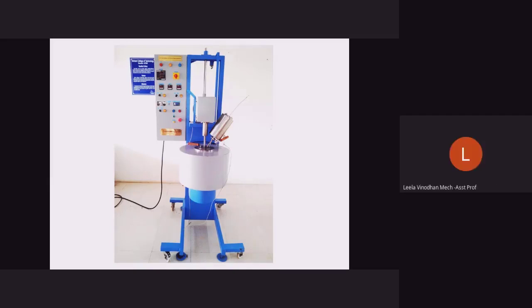So this is the bottom pouring type stir casting furnace. This is basically for aluminum. A similar kind of setup you can also use for magnesium. The problem with magnesium is that it generally catches fire in the normal atmosphere, so you have to do it in an inert atmosphere. If you just expose the magnesium to normal atmospheric air, then it will just burn, and it will turn into ashes.